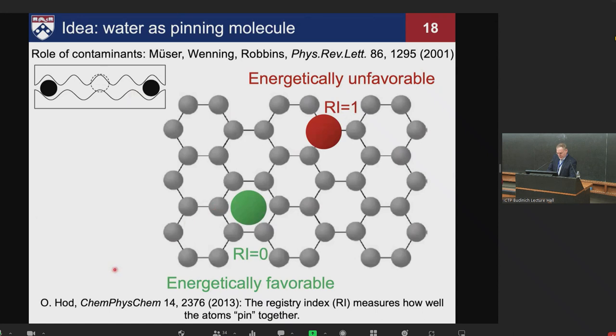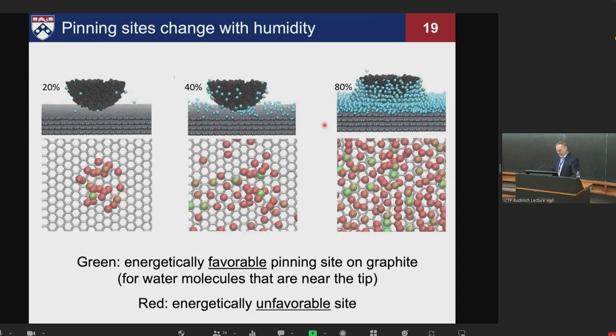There's this very useful concept that Oded Hod came up with, the registry index. When an adsorbate, it could be an atom on the other surface, is at a favorable site, we say that's a low energy interaction that's got a low registry index, and you normalize that to zero. If it's at an energetically unfavorable site, the maximum, most unfavorable site, in this case right on top of a carbon instead of in the hollow sites, we give that a registry index of one, okay? So a low registry index is telling you favorable interactions and thus possible pinning of the interface.